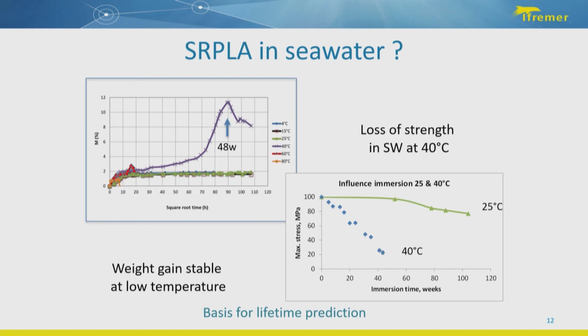In blue, samples immersed at 40 degrees, and you can see that at the beginning, in the first weeks, up to several weeks actually, the behavior was quite stable with a slight drop, but not a drastic one. And then a drastic drop, which corresponds more or less to the increase of the weight gain. The last point at 48 weeks immersion time corresponds to the highest weight gain on the curve. On the opposite, for 25 degrees C, the tensile stress properties were quite stable, even after 2 years of immersion. So this was the basis for the lifetime prediction.